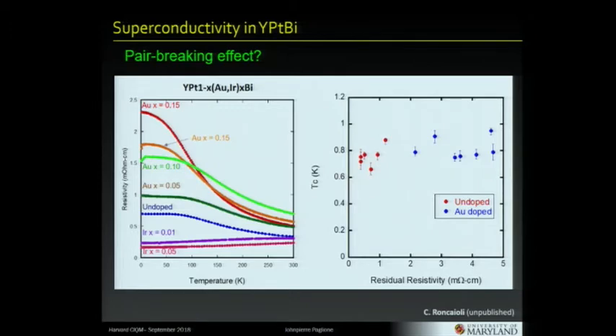I'm not sure exactly. Well, what if you just change it, rather than gold, use something else and change the valence? Yeah. So I have a student doing that, but it's tedious and takes a long time. So we're working on that. The one thing that's also interesting is when we put iridium, which is supposed to go the other way, it actually does become more metallic. So it's a bit challenging because these are nominal percentages and the actual percentages are much smaller. So we're not sure what's happening. But that's one of the things we definitely want to do.